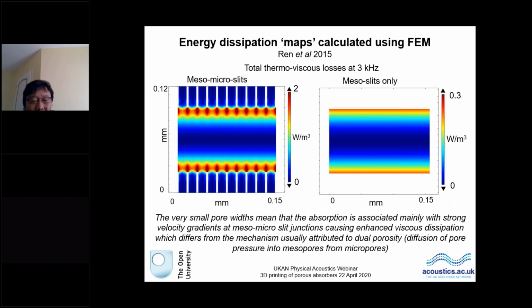on at the intersections. So clearly, there are some things you can do by creating an artificial structure in which you have these kinds of intersections, and that should go in the catalogue of things that you can exploit if you're trying to design a material from scratch to do a target absorption job. And this is showing that something is going on that isn't the same as the mechanism that's usually attributed to dual porosity, which is diffusion of pressure from the big pores into little ones.